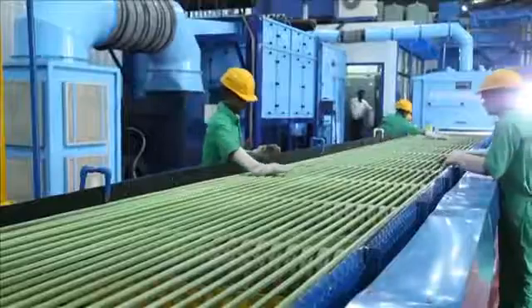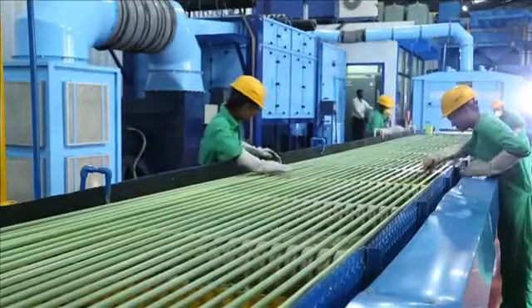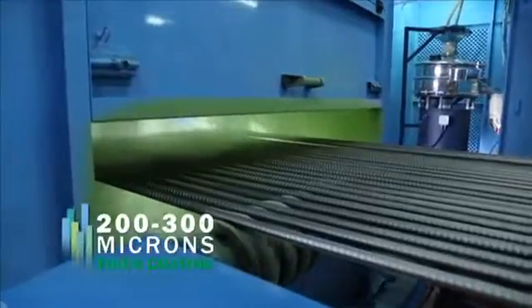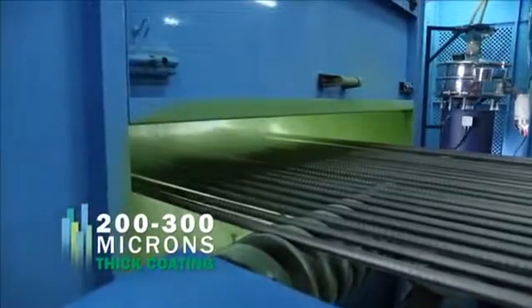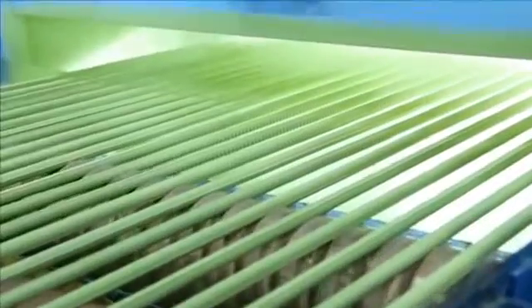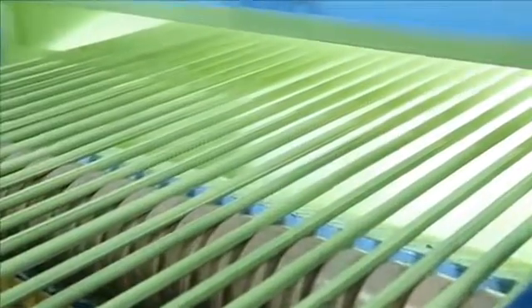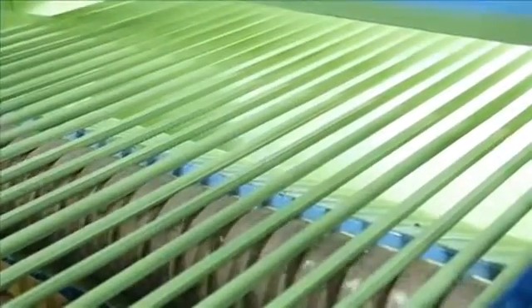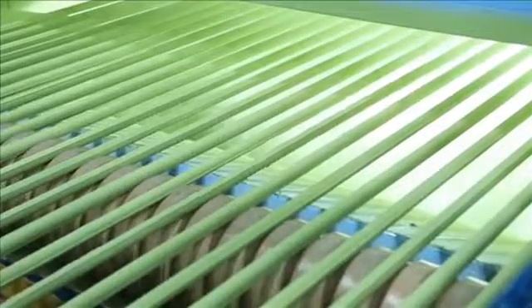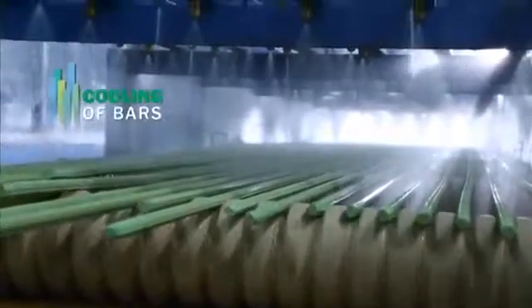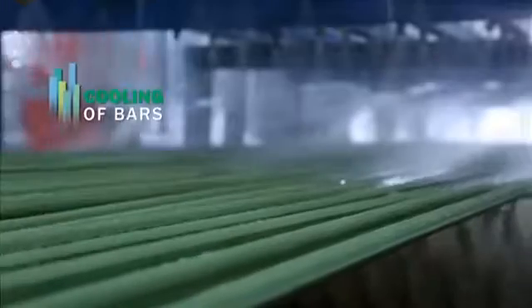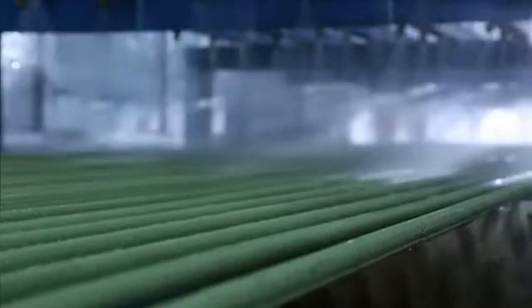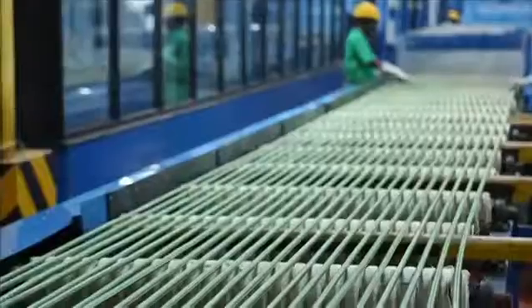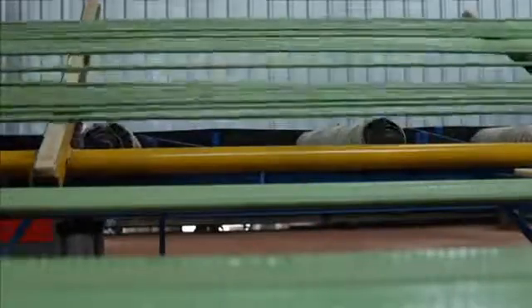When the dry powder touches the hot steel, it melts, flows, and quickly gels as a film, 200 to 300 microns thick, on the reinforcing bars and on deformations, while the residual heat cures the coating. For cooling of the bars, the coated bars, after curing, are passed through a cooling tunnel, where water is sprayed onto the bars to cool them. The bars are then kicked off onto the final inspection rack for testing and inspection.